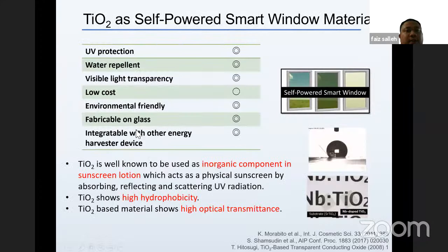Okay, so if we look at TiO2 to be applied as a smart window material, we know that TiO2 is already used as UV protection. It's well known that it has been used as an inorganic component inside sunscreen lotion, which acts as a physical sunscreen by absorbing or reflecting and scattering the UV radiation. And it has also been reported that the water repellence of TiO2 material is good. It shows high hydrophobicity. So if you want to use the hydrophobic ability to repel water on the surface of the window, we can also consider this TiO2.